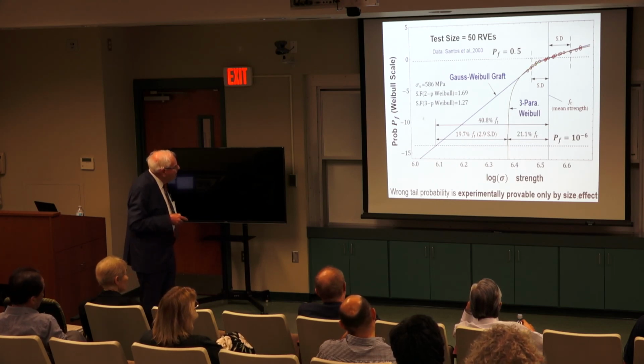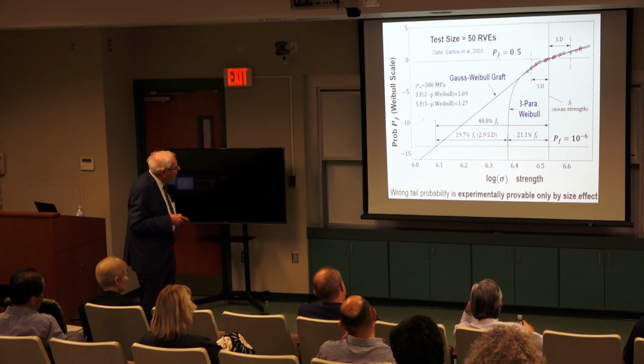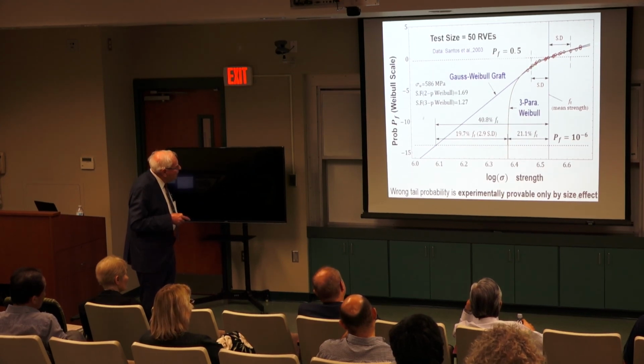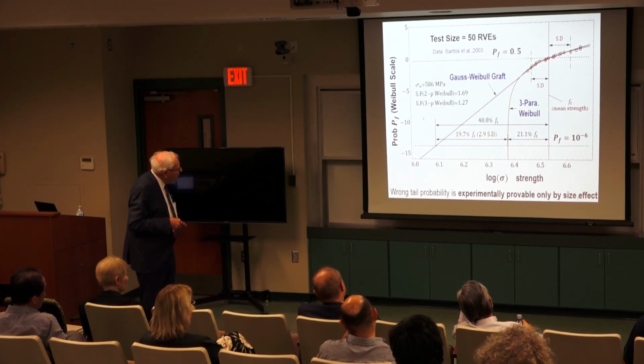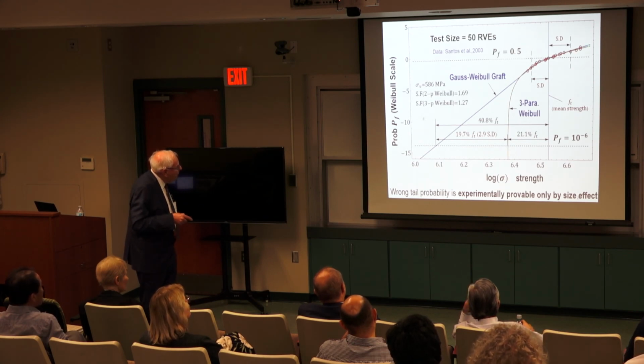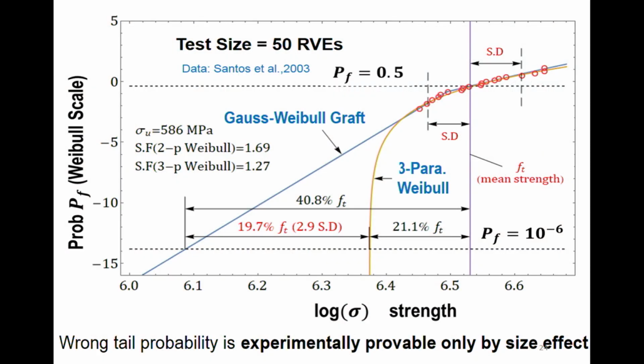These are the data. Of course, some points aggregate several points. And this is what is done in most literature. They put a threshold, they have this curve. And then if we extrapolate it our way, with the grafted Gauss-Weibull distribution with the transition, you obtain this diagram.